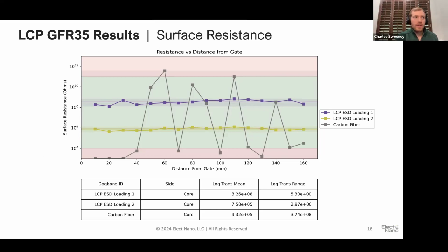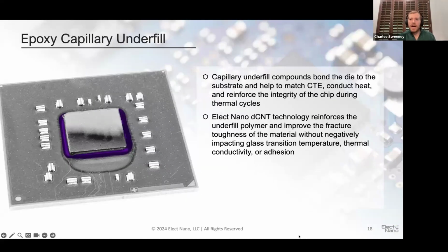Now I'm going to switch gears into some of our epoxy applications. In semiconductor manufacturing, once you have your die, one of the next steps is typically to do a flip chip or multi-die stacking 3D assembly. You're basically putting silicon chiplets together onto a substrate so that you have something that can be encapsulated. When you do a flip chip process, you flip it upside down, and you've got solder bumps that connect the chip to the substrate, but there's a gap in between there.